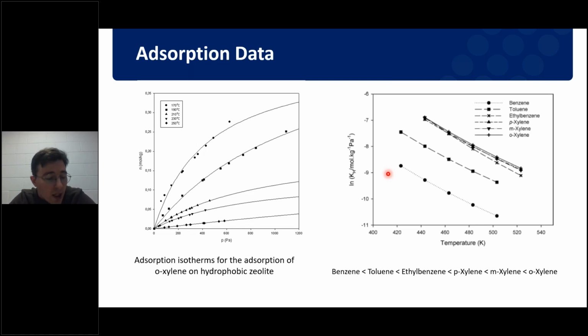The main reason this is up here is that we can see this sorption isotherm really deviates from linearity. That suggests we have some inhomogeneity or heterogeneity with regards to the sorption sites on the zeolite. And that is consistent with the results we find with its surface energy. Our surface energy is heterogeneous, and we can see that from its surface energy profile measured in inverse gas chromatography. That heterogeneity is reflected in the non-linear uptake of our probe molecules.